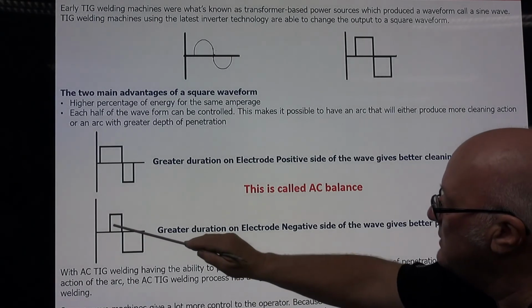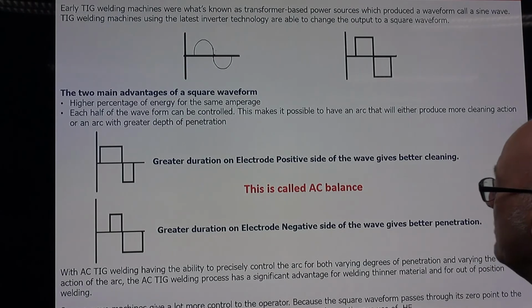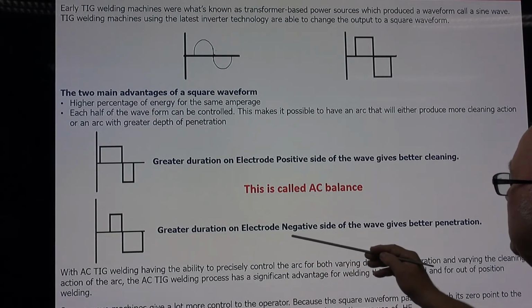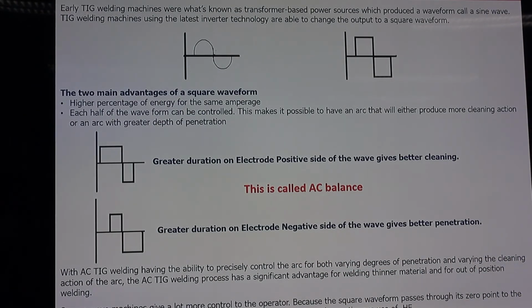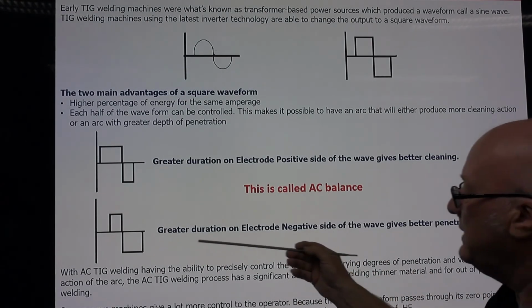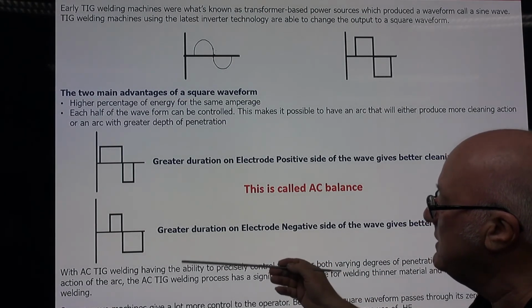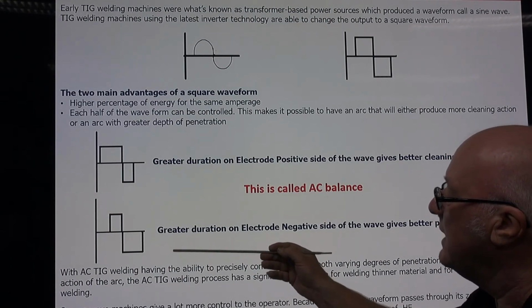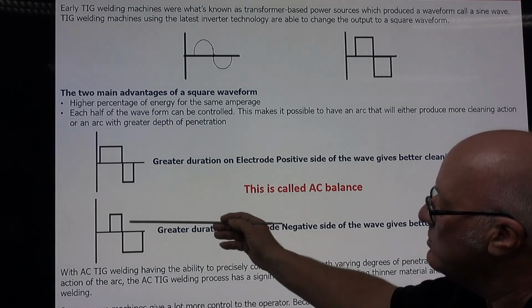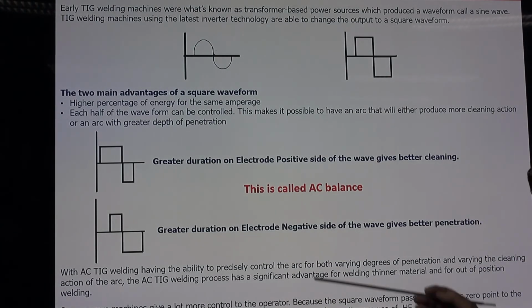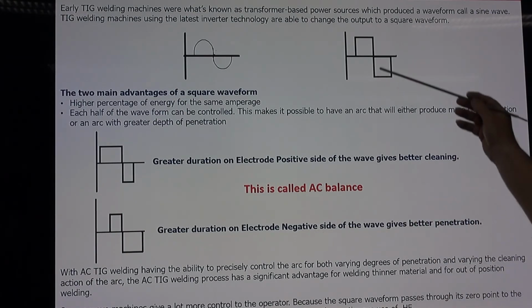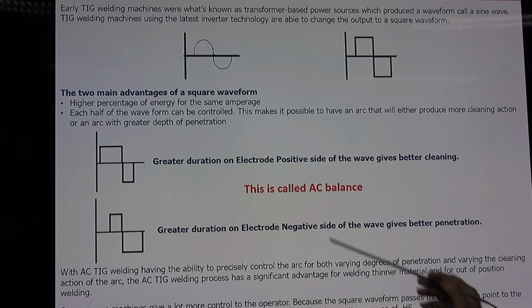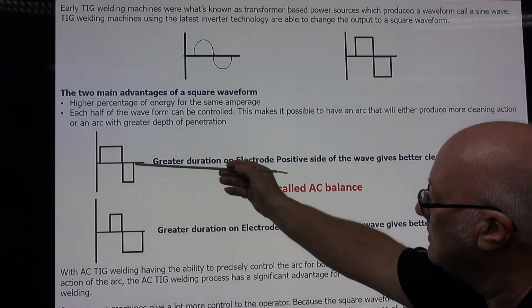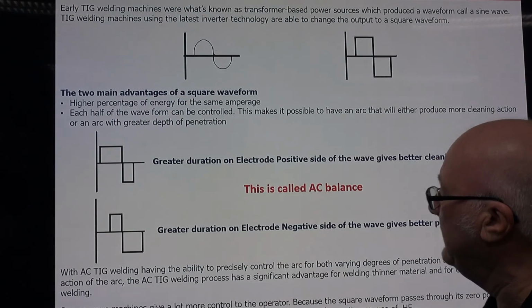Now, we can also change it so we have the bottom half staying on longer. This will make the electrode negative, and this gives us more penetration into the job. The advantage of running it this direction is that we can put more energy into thicker materials and get a higher amount of input, and also the tungsten runs cooler. So AC balance has several advantages, but just beware of its downsides. When you have a balanced wave, it looks like that. If we have an unbalanced wave, it can look like the top one here or the bottom one there.